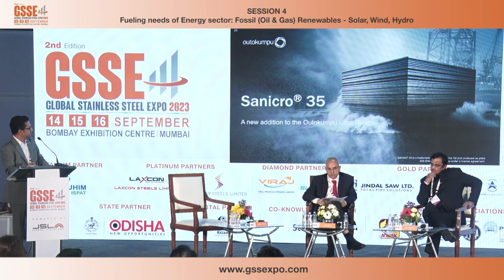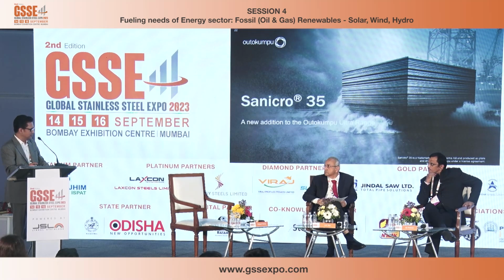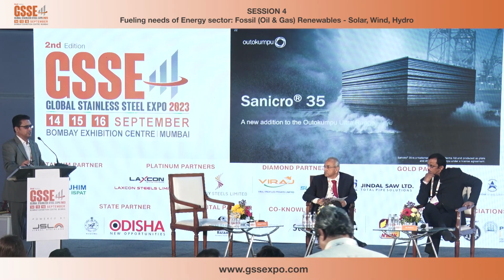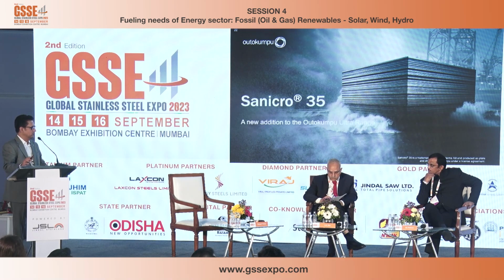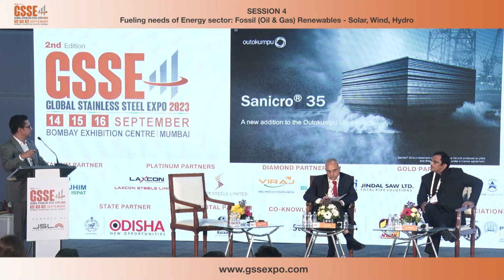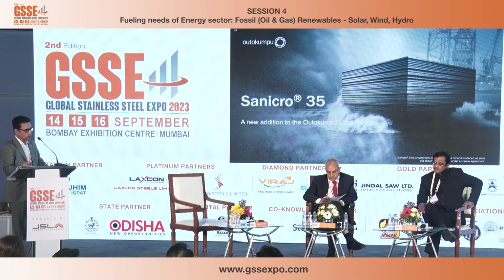This is one of the new additions, Sanicro 35, which Outokumpu has added. In fact, this is a grade by Alleima, earlier Sandvik. So what was happening was people were using Super Duplex 2507, and if Super Duplex was not sufficient, they were switching directly to 625 because there was nothing available in between for those applications. So there was no solution. This grade has tried to cover that part or bridge that gap.